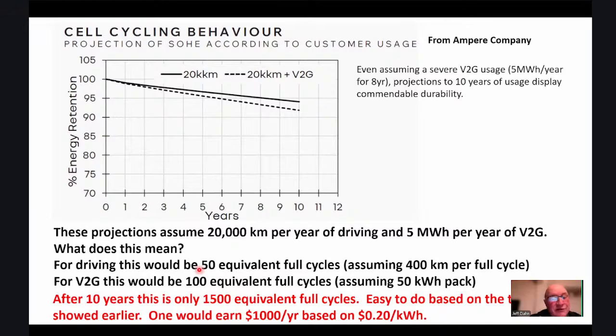So that's very little. And for vehicle to grid, if you have the 50 kilowatt hour pack, 5 megawatt hours is only 100 cycles. So over 10 years, this is only 1,500 equivalent full cycles. That's easy to do based on the test results I've showed you before. And if you were in my province and you were earning 20 cents a kilowatt hour for the 5 megawatt hours per year, you'd get $1,000 per year. Okay, so you get paid for just leaving your car plugged in. And it hardly harms the battery at all.